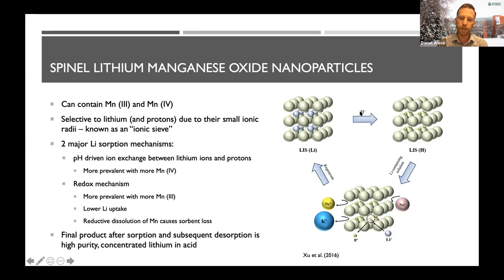And there's always protons, H plus, in water. That's the acidity, right? That's where pH comes from. So water, H2O, is always dissociating. It's separating into H plus and OH minus, even in a glass of water. But you can leverage this. So you can imagine the way that this works. I make this mineral, it's nanoparticulate. I might bind it together into bigger particles depending on the application, but I simply put this material into the brine, which is a mess. It's just got this 40, 50, 60, 70 ppm lithium. But because this material is highly selective, things like manganese, sodium, potassium, all these other cations simply cannot get into the structure. And so the only thing that can fit in there when it's in the brine is the lithium.